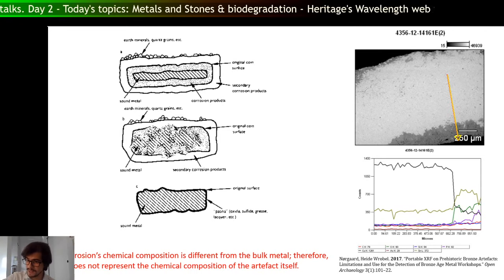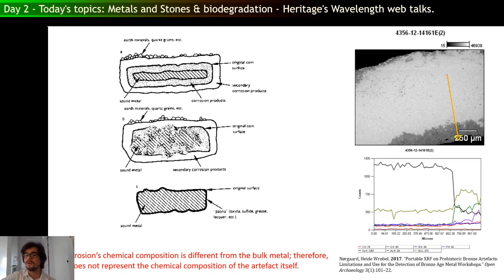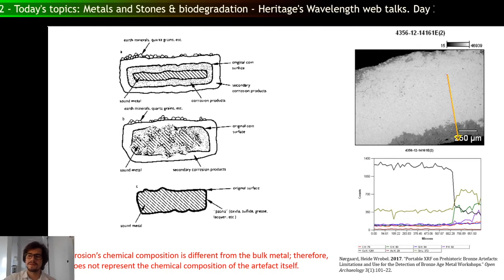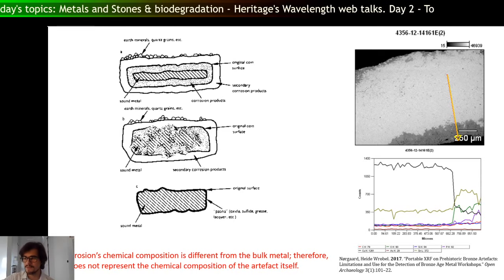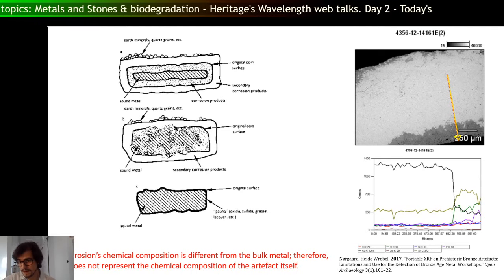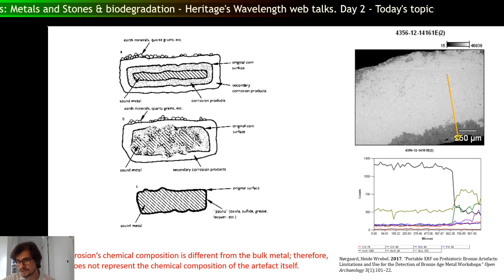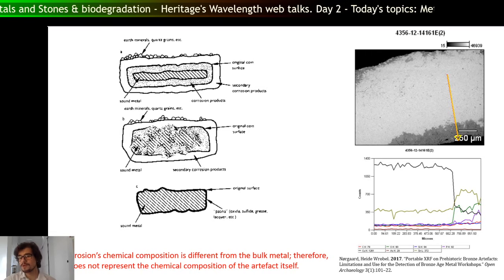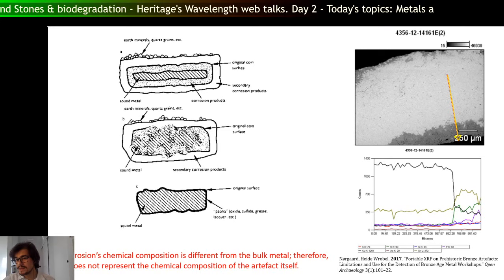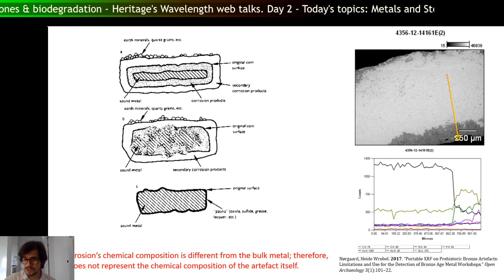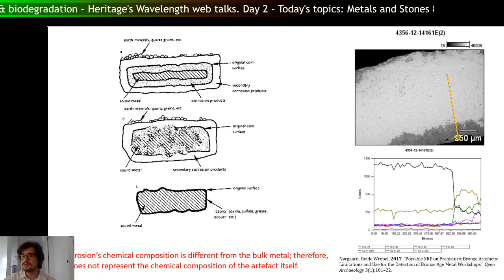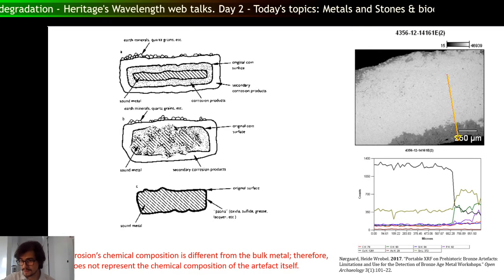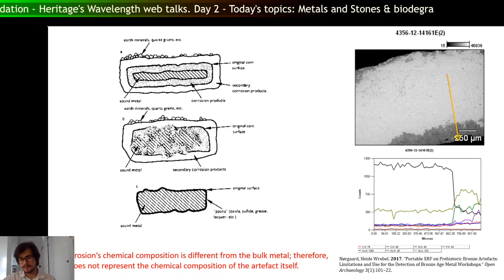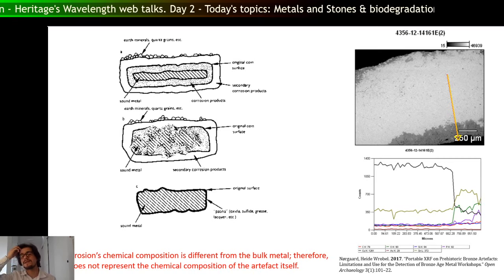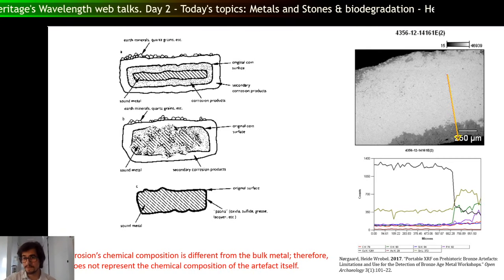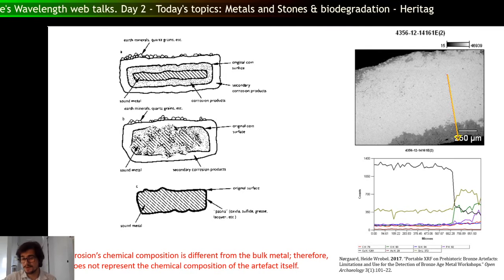When you do chemical analysis, going back to that discussion, 99% of the times you will get information on the surface. So this chemical composition that you measured and assumed is the chemical composition of the object, in fact, is not. It represents the chemical composition of the upper layer. It does not necessarily mean that that composition represents the bulk metal. This is why some chemical composition analyses are done on sectioned metals. But for that, you have to cut your material, you have to sample it.